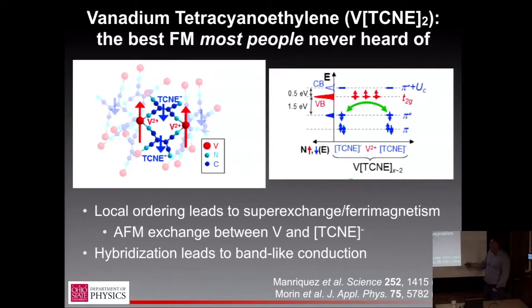But the basic idea is you have these small molecules, TCNE, which are shaped like an H, with cyano groups at the terminus, and they're connecting between adjacent vanadium atoms. And the idea here is then you have either some super exchange or double exchange interaction where the vanadium starts off with 5 d electrons, gives up 2, that's what's shown schematically in this diagram, to charge the TCNEs to minus. In addition to the charge, that electron carries spin, so you have 1 spin pointed down, and the remaining 3 vanadium spins pointed up. So while this direct interaction is antiferromagnetic, the vanadium sublattice is ferromagnetically ordered, so this is called ferrimagnetic order. If you add up all the spins here, you get a net spin of 1 Bohr magneton. So it basically acts pretty much like a ferromagnet.